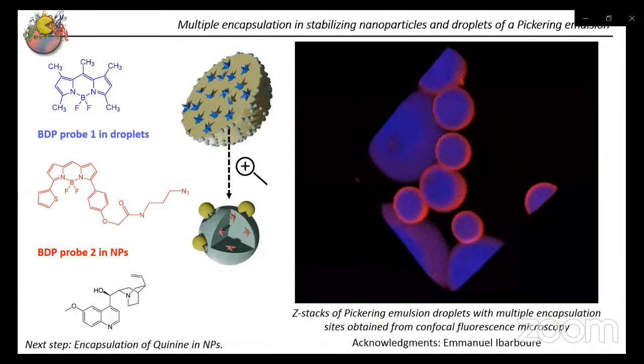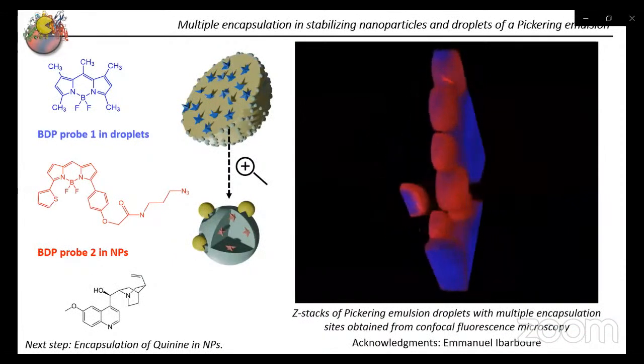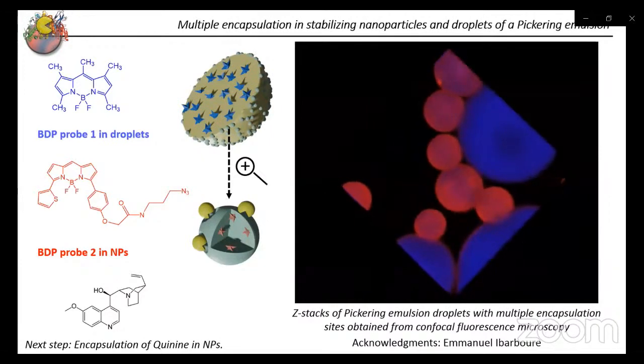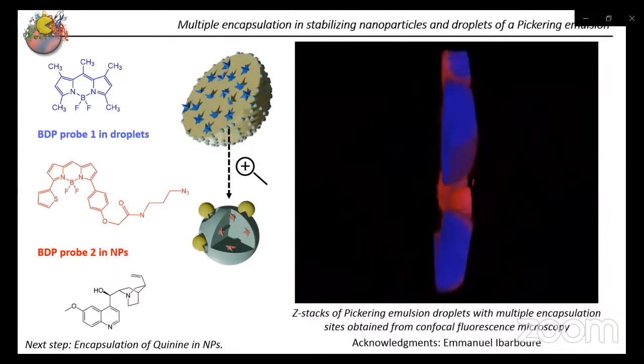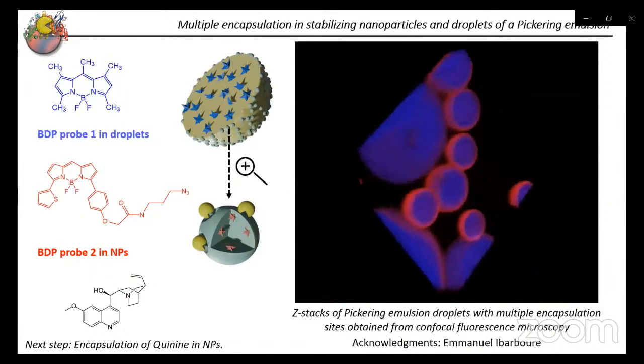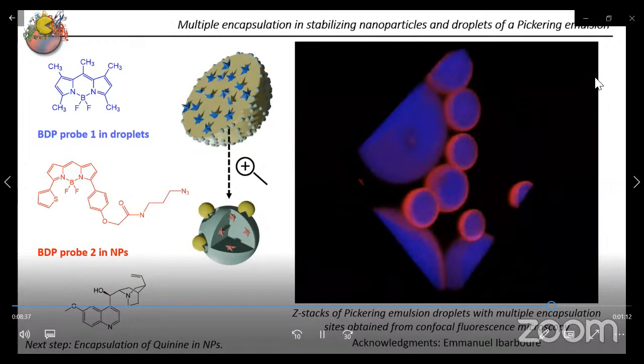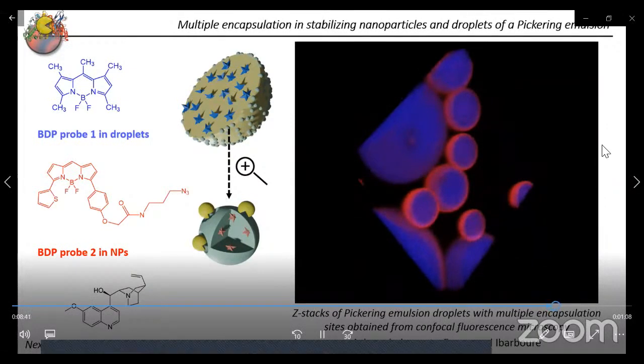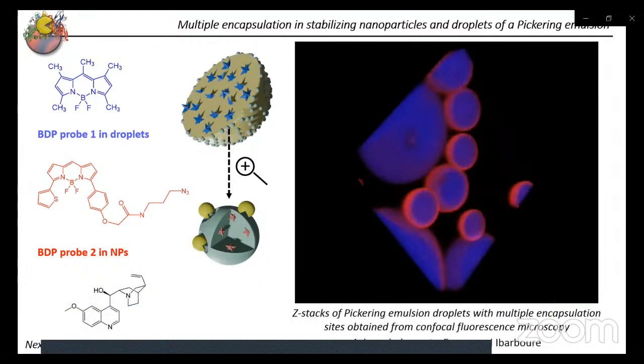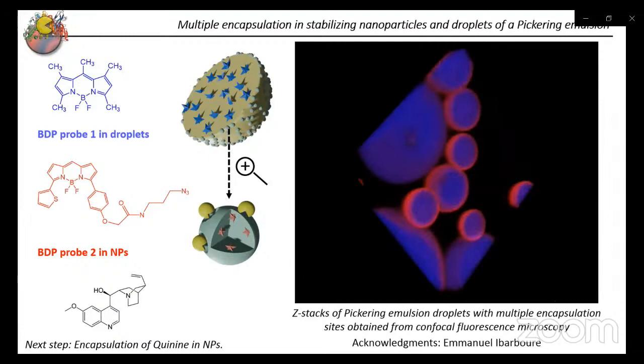With the system, we were also curious whether we were able to encapsulate two different compounds, one inside the droplets we stabilize, and another inside the stabilizing nanoparticles. To do so, at the nanoprecipitation step, we put the polymer and the probe together, and this leads to the formation of nanoparticles with the probe inside. As you can see on the right, these are the Pickering emulsion droplets with the encapsulation of the red probe inside the nanoparticles, so at the interface, and the blue probe inside the oil droplets. The next step, which is currently ongoing, is the encapsulation of a drug.